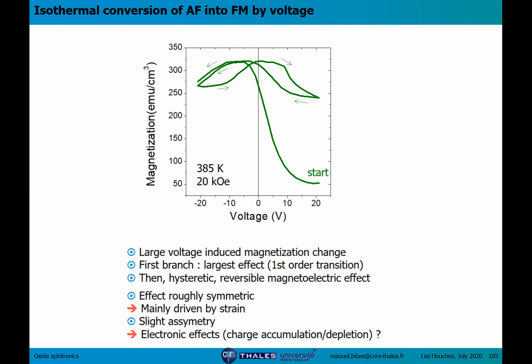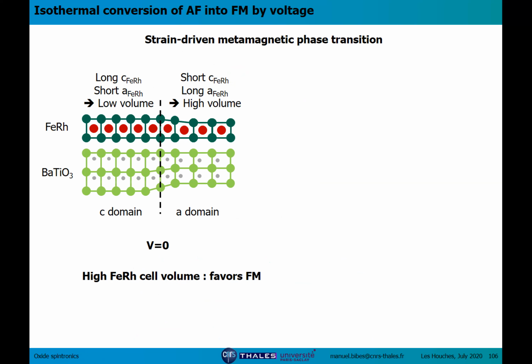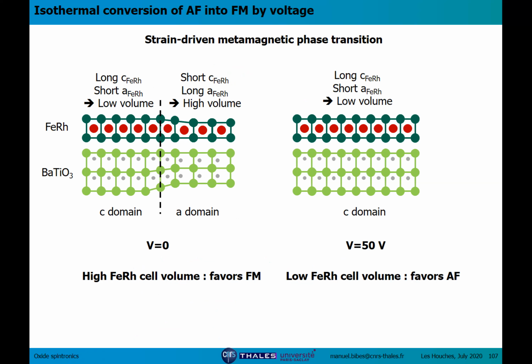driven by strain. As I will show in the next few slides, we don't seem to have a very strong effect from charge accumulation or depletion from the ferroelectric BTO, because this should result in a strong asymmetric response. So let me go quickly through that.